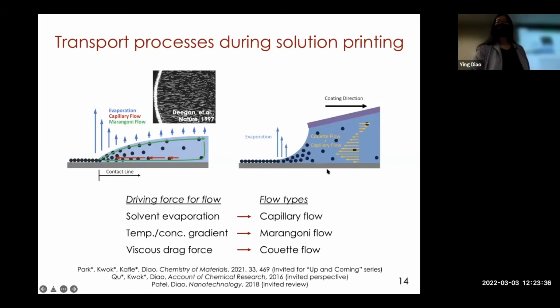And if we start moving the substrate or the ink applicator, we introduce another flow type. That flow is driven by the substrate moving; basically, the ink wants to stay with the substrate. That's called viscous drag force. And the flow resembles flow between parallel plates, which we call Couette flow.